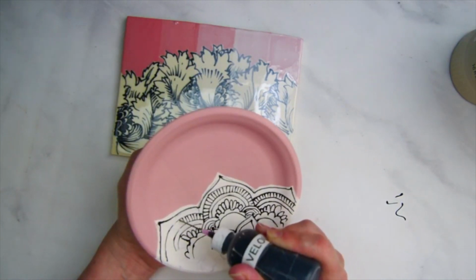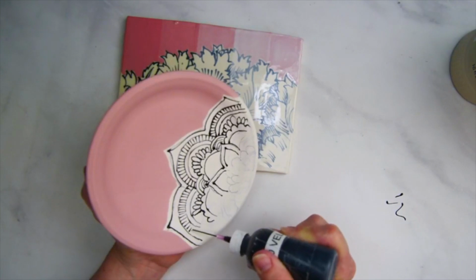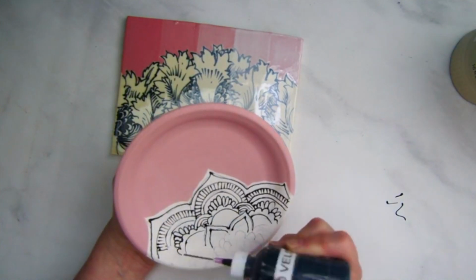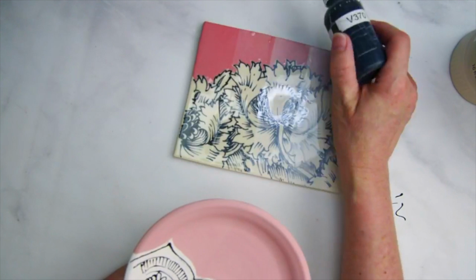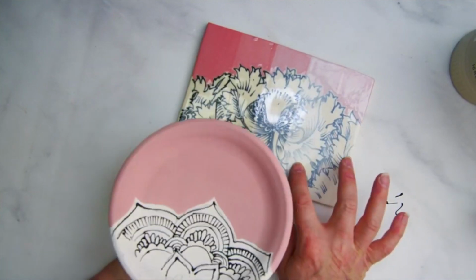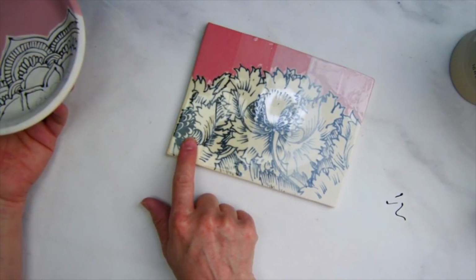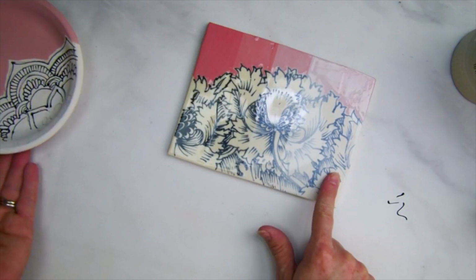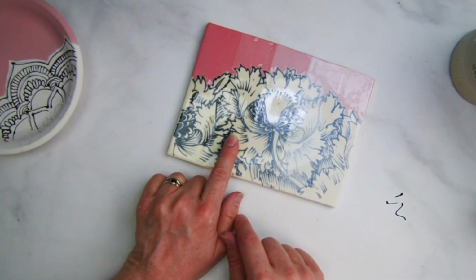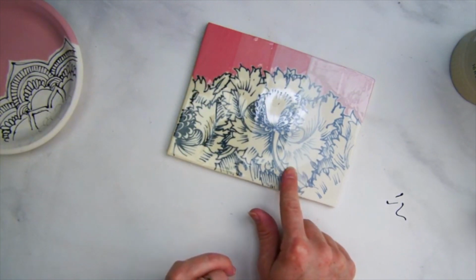Now I think instead of doing all of the underglaze on this for the video, I'm going to set this aside and I'm going to talk about mixing Celadons. So, as I said, this sample tile is fired to cone 5. These are the same underglazes, so we'll have a similar sort of effect. This is completely mixing clear. This is completely snow. This is 50-50 snow and clear, and this is 75% mixing clear, 25% snow. This is 75% snow and 25% mixing clear.